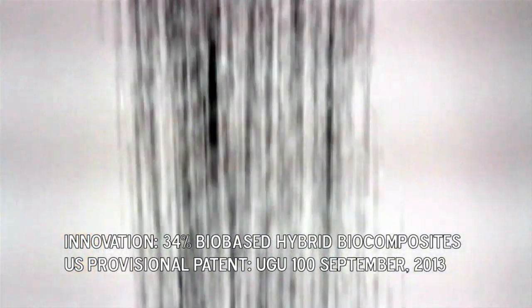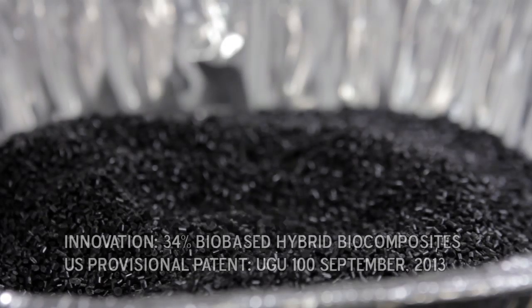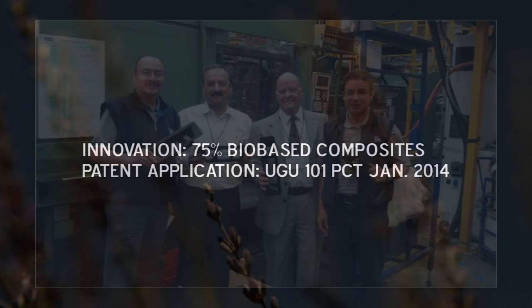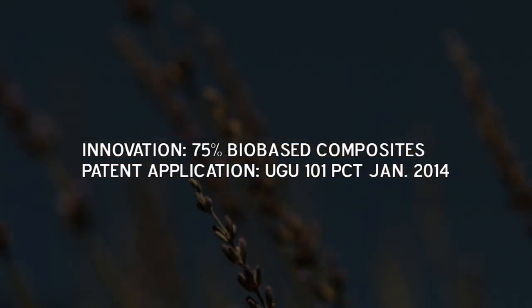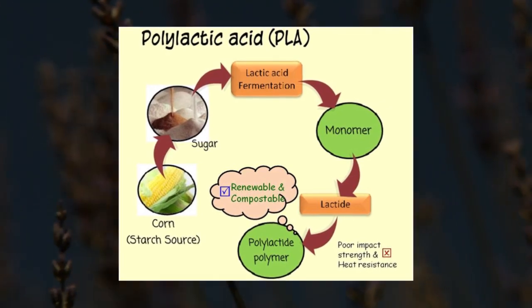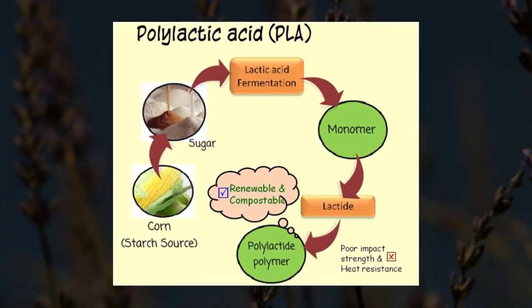In the next part of our work, we have increased the bio-based content of the parts by incorporating miscanthus in combination with biocarbon and have successfully produced various car parts. To further increase the bio-based content, we have developed formulations with polylactic acid, PLA, a renewable resource-based bioplastic.